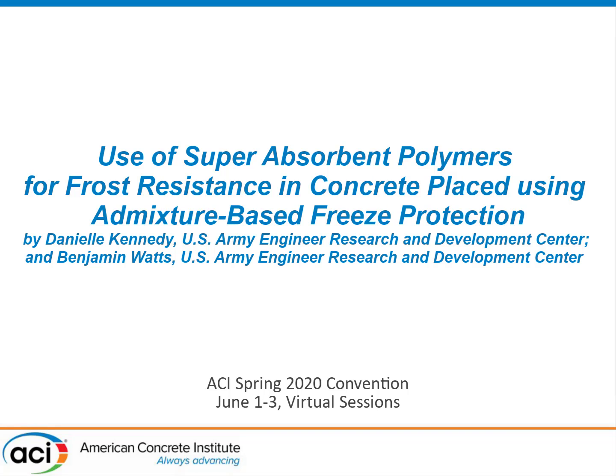We did slump testing in the very beginning, and it was kind of difficult to dial in what the slump would be. At some points, it would be a full slump, but it was still very workable. We were working in a cold space, so you want something that's very workable and not going to harden immediately. But slump was not our number one goal with this. It was trying to hit that air entrainment target, which sometimes, as I'm sure a lot of you know, is hard to meet along with your slump when you're working with a combination of different admixtures. So we did focus on slump and work with it, but that was not our number one goal.